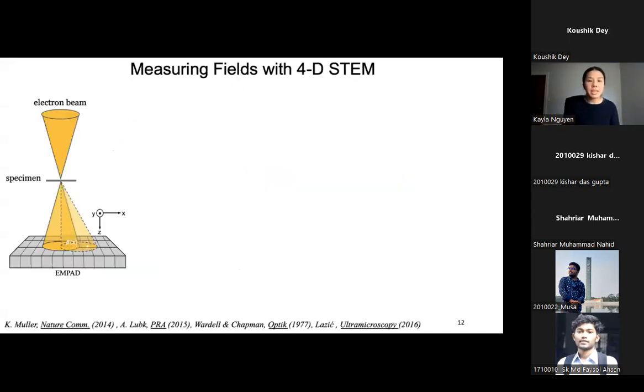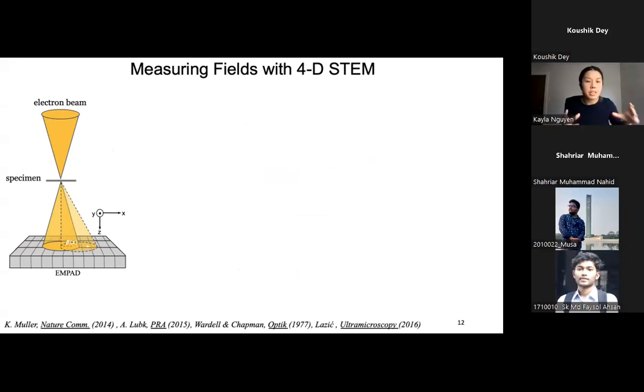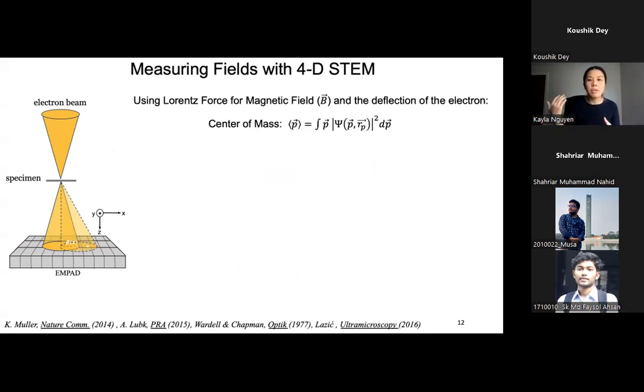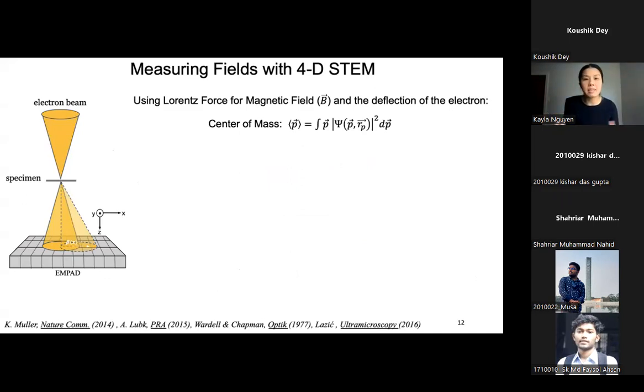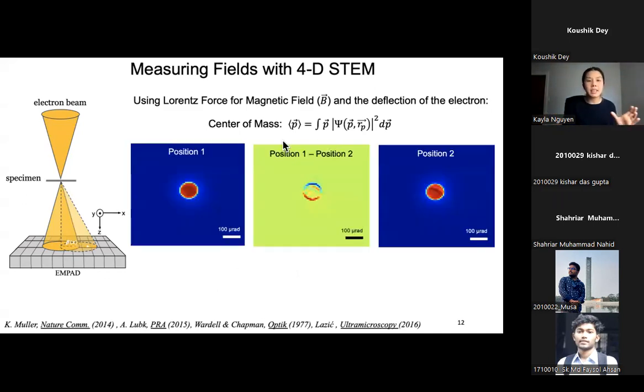And so what we can do is we can take our electron beam, put in a magnetic sample, and take our diffraction pattern, and from that try to get back information related to the magnetic field. And so within the diffraction pattern, we can calculate the center of mass. So visually, what this means is that these are electron diffraction patterns at position 1 and position 2. Electron diffraction patterns are basically the intensity of the wave function. And what we want to do is measure the change in momentum. So this equation is basically saying that if we take two positions, for example, position 1 and position 2, and we subtract them from each other or look at the average change in momentum, then we should get a deflection related to the local magnetic field.